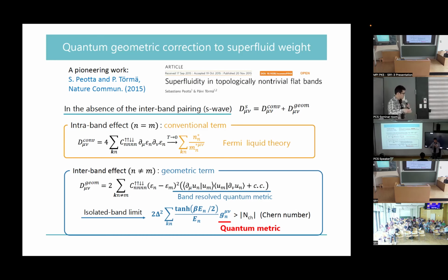Interestingly, they also found a topological bound for the superfluid weight arising from the quantum metric. Because the quantum geometric tensor has semi-definite properties, we can show that this term must be larger than the absolute value of the Chern number. So this is the topological bound. That means if the band is topologically non-trivial and characterized by finite Chern numbers, we will see a finite contribution from the quantum metric in the superfluid weight.